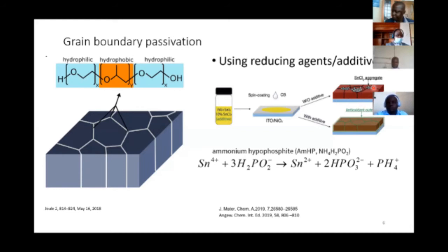because they act like charge trap centers. Now, what people are trying to do is that, yes, we are still going to apply tin fluoride, but we have to get rid of these aggregates or other phases that are formed on the surface. That leads to the introduction of another additive, which is called a co-additive. People have seen that the major co-additives react with these phases to form a complex. This complex can either passivate the surface or passivate the grain boundaries.